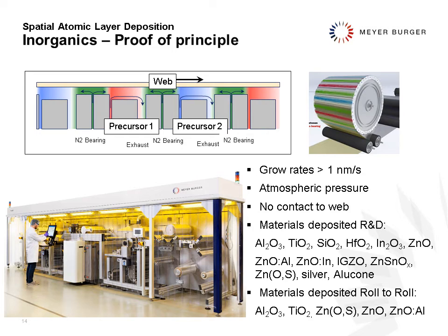Now, when we talk about inorganics, for roll-to-roll application, we have this spatial ALD, atomic layer deposition, configuration. So the principle of ALD is to use two precursors and expose the surface to these two precursors at different moments.